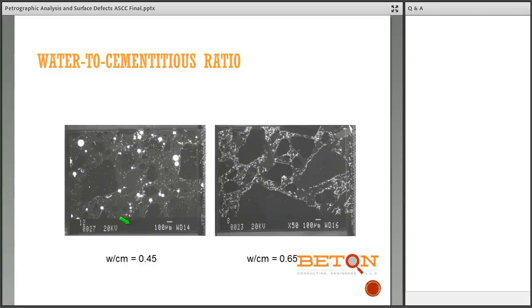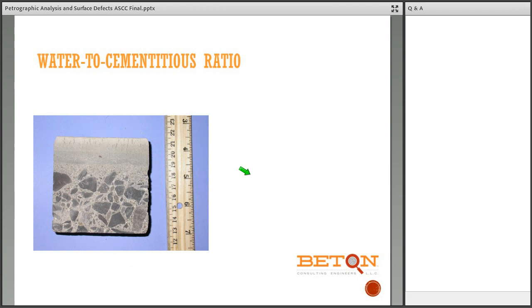Another interesting method would be Wood's metal intrusion porosimetry. Basically, these are the same magnification. We've forced Wood's metal into the paste, and get an idea of what kind of porosity there is in the paste. The Wood's metal under a scanning electron microscope will light up like you see on the right here. This one was a higher water cement ratio of 0.65 versus a 0.45. You can see the difference in porosity in the paste. Wood's metal is a metal that's liquid in hot water, so we're able to push it into the concrete without affecting it. Okay, this is a core that we had received, and it makes you wonder what went on there.